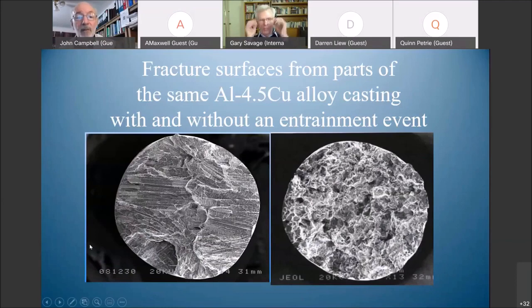And here we've got a 6mm diameter tensile test bar, and what you can see is that the bifilms have been pushed ahead by grains growing out from this direction and grains growing out from this direction. And this heap in the middle here, this is a heap of spare bifilm that's just finished up as this central mountain range. And this is out of the same casting, but this is a bit of the casting that's solidified more nicely. And here it's just covered in very tiny bifilms. These bifilms are large because of a big wave which happened at this side. But in this part of the casting, there are no big waves, and these are just the natural population of bifilms controlling small cracks.